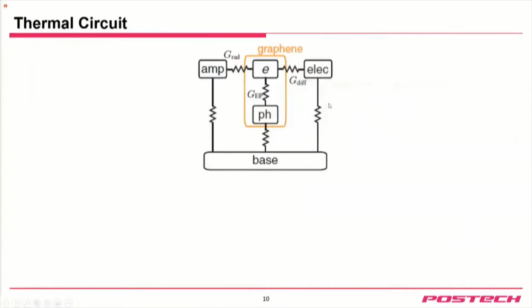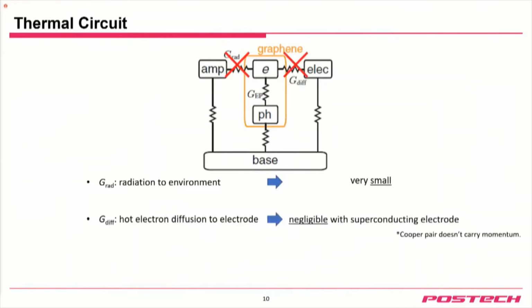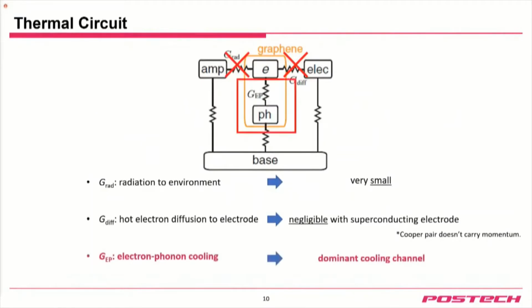So when graphene absorbs energy, it will increase the electron temperature, but it will eventually lose its energy back to the bath through multiple channels. There are three channels we can think about. First is black body radiation, but because we are in the millikelvin range, this is almost negligible. Another is diffusion of the hot electrons out to the electrodes. But remember that our electrodes are superconducting, and superconductors are perfect thermal insulators. So we can ignore this; the diffusion cooling channel almost vanishes in the Josephson junction structure.